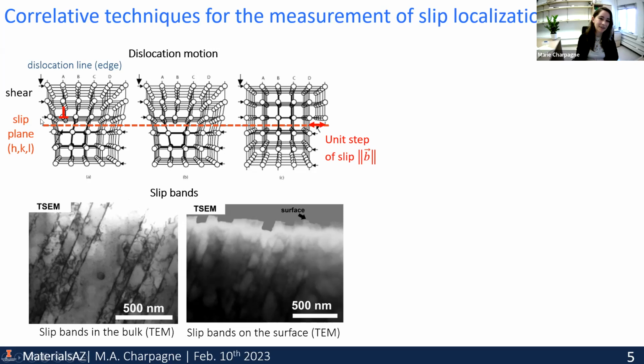The slip band results from the motion of dislocations in the crystal lattice. Each dislocation is defined here on this schematic as this half plane that glides on its slip plane. And as it exits onto the material surface, you have a unit step, a very small atomic extrusion of unit vector b. That vector has a direction and also an amplitude, and that's characteristic of each material.